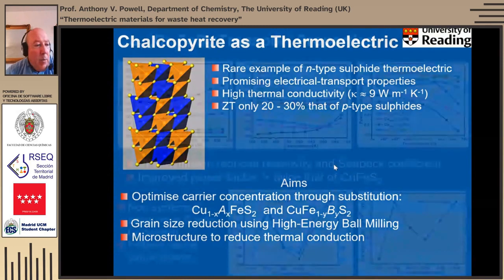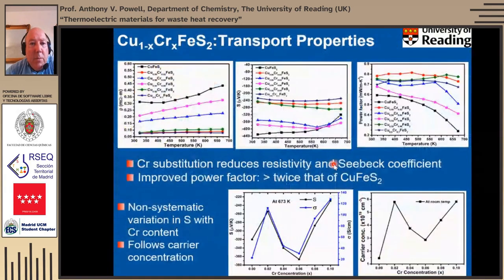So I'll just choose one example from this system, which is the copper chromium system, where we've substituted copper with chromium. And what we find is that if we do that, we improve the resistivity. So the resistivity falls quite dramatically. And also, surprisingly, we don't impede the Seebeck coefficient as much as we might have expected for this reduction in resistivity. So although the Seebeck coefficient does indeed get smaller in absolute terms, it's not as much a reduction as we might have expected, and therefore we almost double our power factor compared to the end member phase.